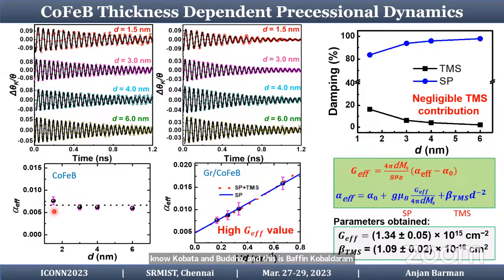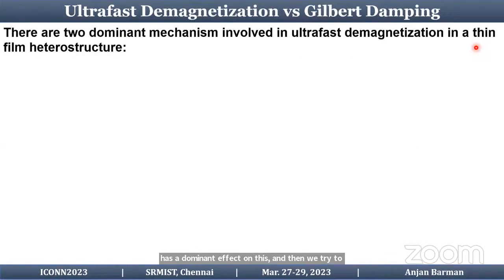For this, the damping doesn't vary with the cobalt iron boron thickness, whereas in this case, it varies almost linearly with the cobalt iron boron thickness. So we did the modeling using spin pumping and two magnon scattering, and we found that the spin pumping has a dominant effect on this. And then we try to understand it in terms of different models.